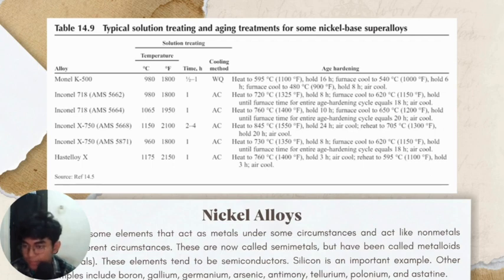Nickel has a natural tendency to combine with sulfur and oxygen, and it is found in nature as nickel sulfide and nickel oxide. In heat treating nickel alloys, it is critical to minimize exposure to sulfur in fluids, lubricants, grease, or gaseous form.